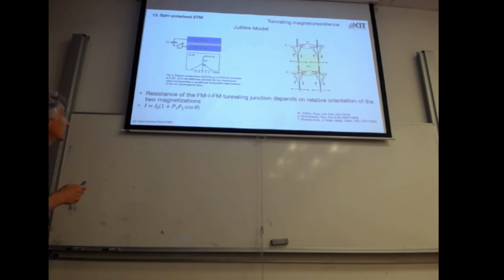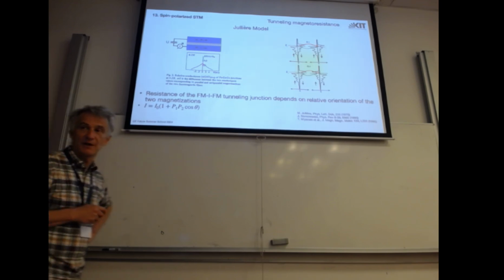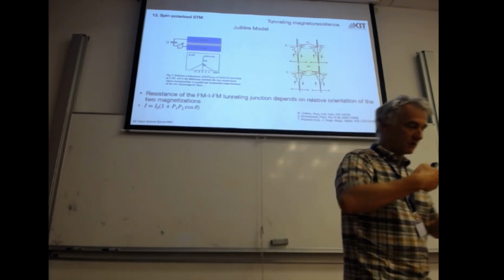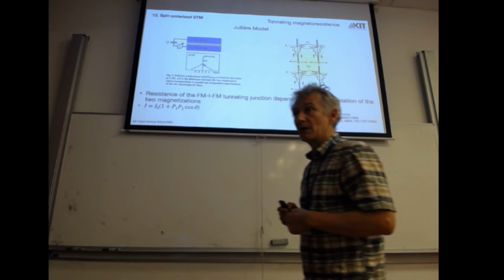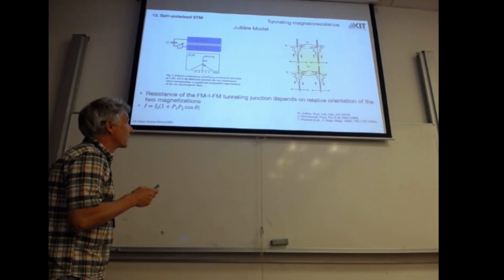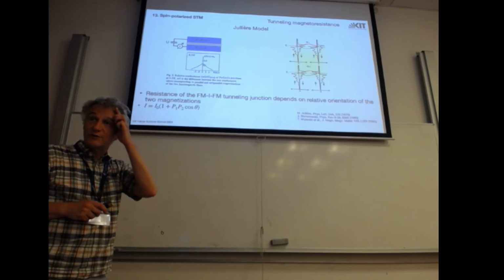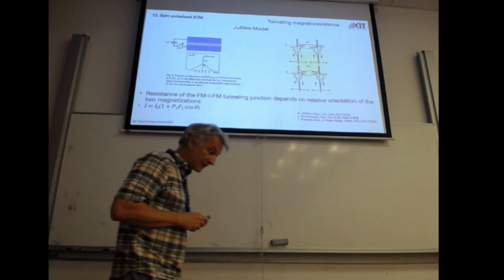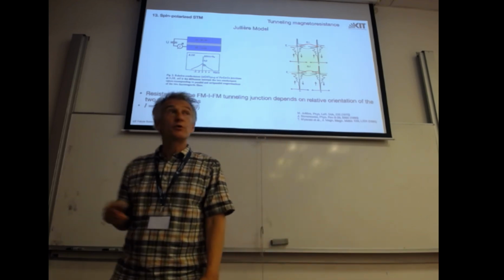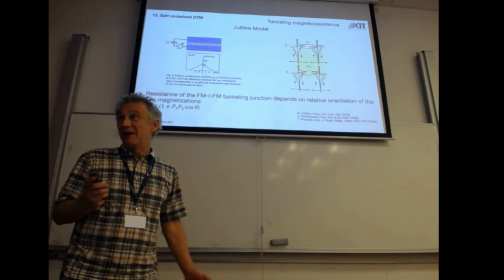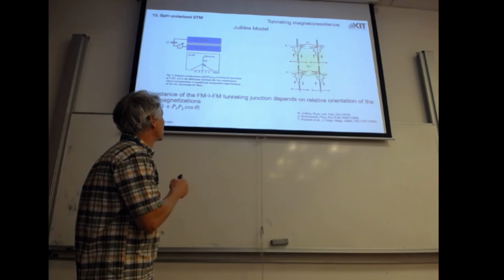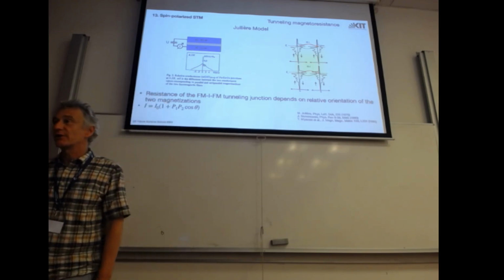This early experiment showed that there is a difference in conduction if the two magnets are magnetized in the same direction or in opposite directions. In this early publication, the difference is about 15%. So the tunneling current changes when we go from parallel to anti-parallel magnetization. This can be interpreted very simply. We have the spin polarized density of states on both sides, and we again take a Bardeen theory, but now for two channels. During tunneling, of course in vacuum, nothing can happen to the spin of the electron. And if you have a well-behaved insulator, the spin of the electron is also conserved during tunneling.